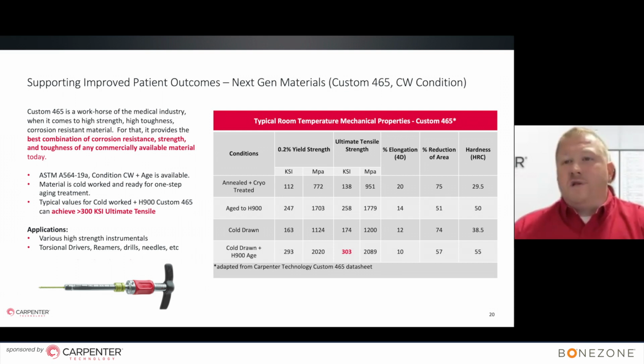Custom 465 has been supplied in the cold work condition, ready for a single stage aging treatment for a very long time. But as of 2019, we also lobbied to have it added to the ASTM A564. So just from a communication standpoint, the ASTM A564 revision 19A includes the condition for specifically calling out cold worked for this particular product. So I would encourage you and your team to explore the benefits of the cold work condition for 465 as you potentially look at design changes and design criteria, leveraging the cold worked condition and seeing here on the slide that you can approach over 300 KSI in your instrumentation or design.